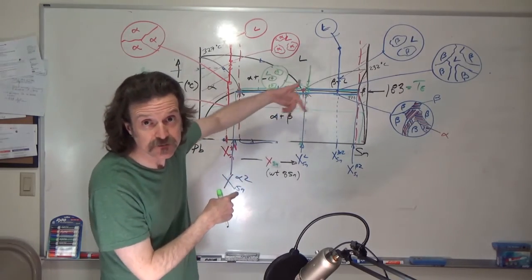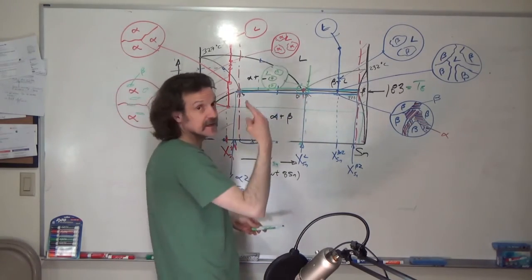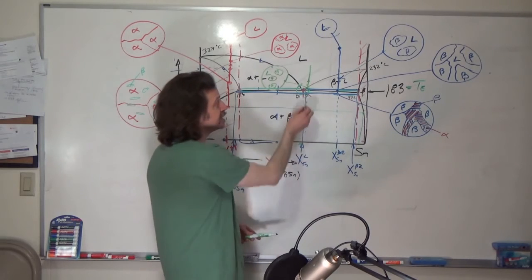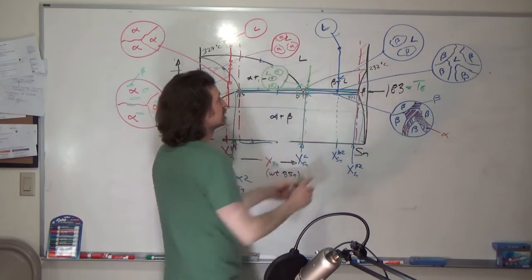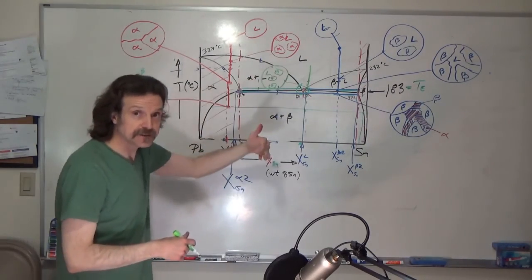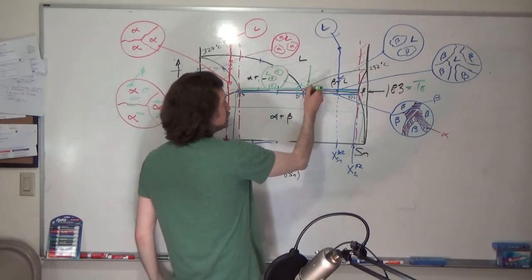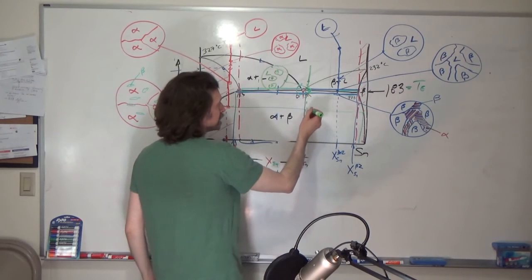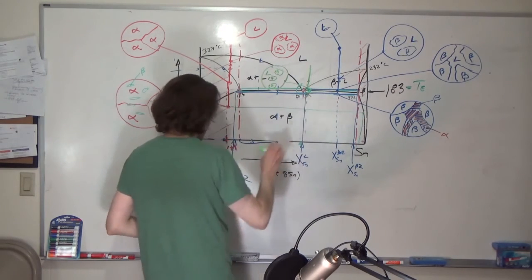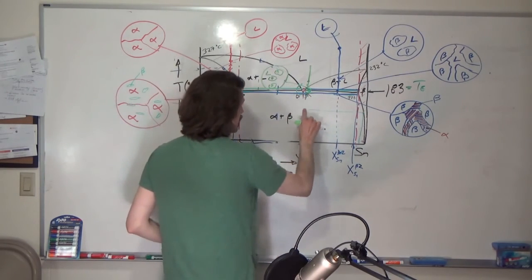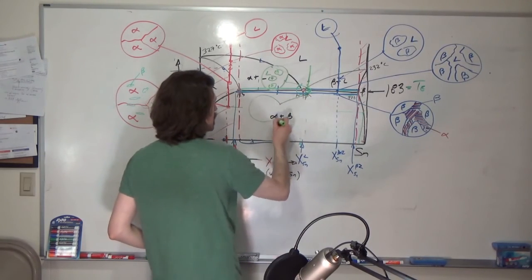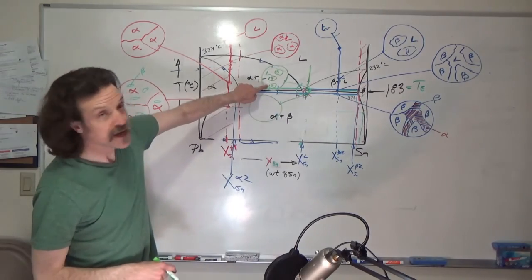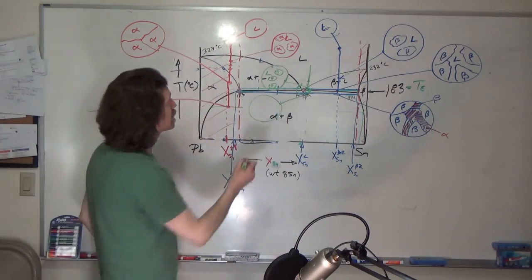And that again comes from our inverse lever rule, right? Because the phase fraction of beta is that little slice divided by the total length. And now that I drop down below the eutectic temperature, those beta crystals stay.